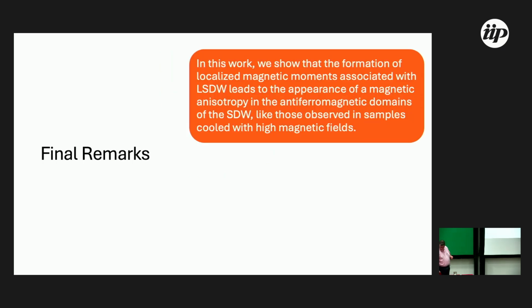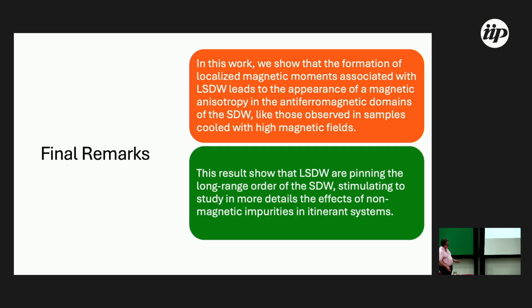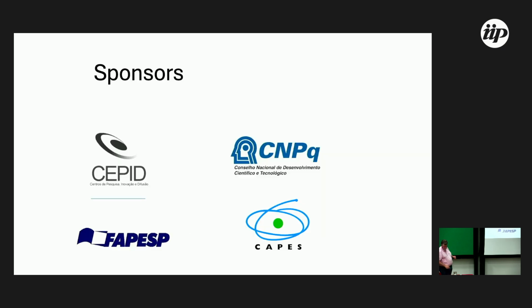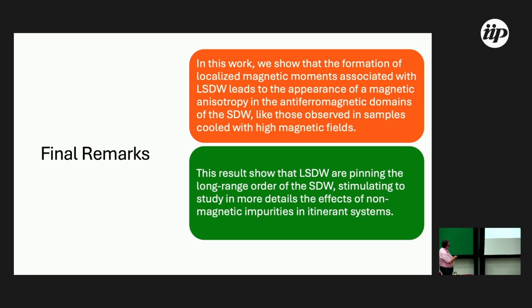Finally, the formation of the localized magnetic moments associated with this local spin density wave leads to the appearance of magnetic anisotropy and antiferromagnetic domains of the spin density wave, observed when cooling down with high magnetic fields. And it shows the pinning of the long-range order of the SDW. It stimulates studying in more detail the effect of non-magnetic impurities in itinerant systems. For the end of my talk, it is important to have a calculation of the influence of the impurity in the chromium matrix.